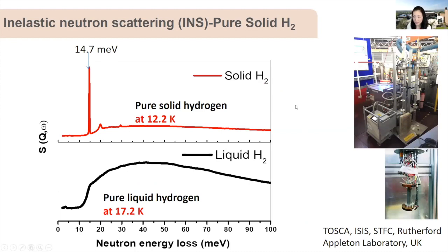So this is our typical INS pattern for solid hydrogen in bulk, collected on the TOSCA instrument at the RAL lab in the UK. This is the sample cell we have been working with. The experimental procedure is we seal the cell, attach the cell to the center stick, and insert the center stick into the cryostat. And then we pressurize the system with hydrogen, and then cool down the whole system to 12 Kelvin. So then we know this is solid hydrogen inside. We shine the beam through and collect the data.